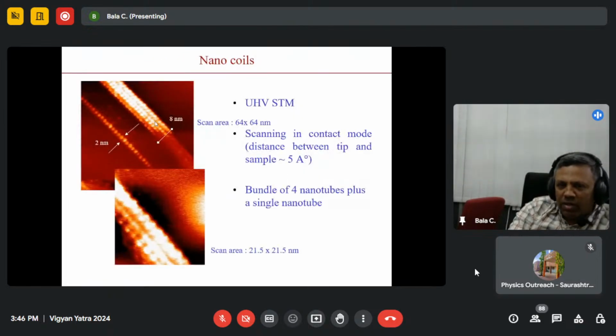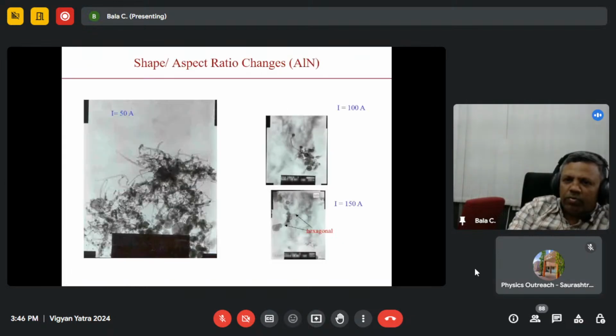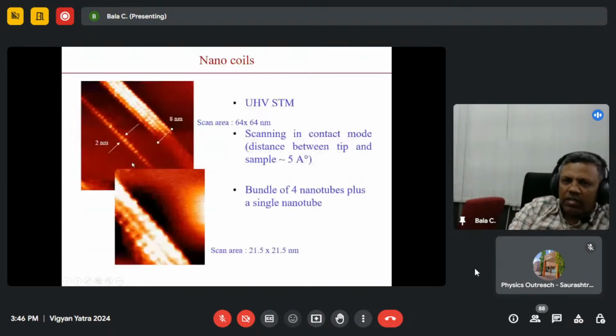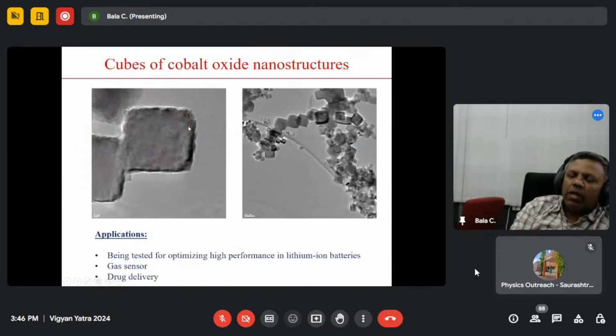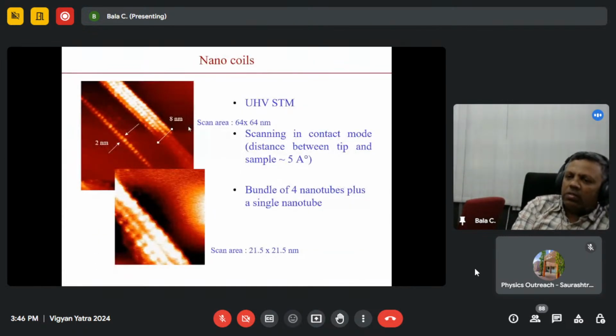I can get different shapes also. These are nanocoils of the same material for different parameters. If you see here, these are nanowires, and then with the same material you can get nanocoils. Basically, that all depends on the nucleation and growth, and nucleation and growth is decided not only by the material but also by the thermal availability, the quenching, and the growth mechanism.